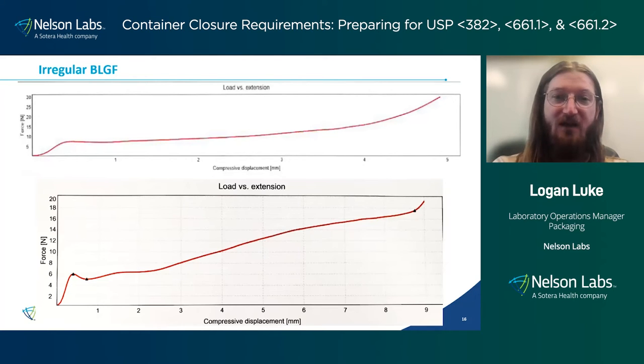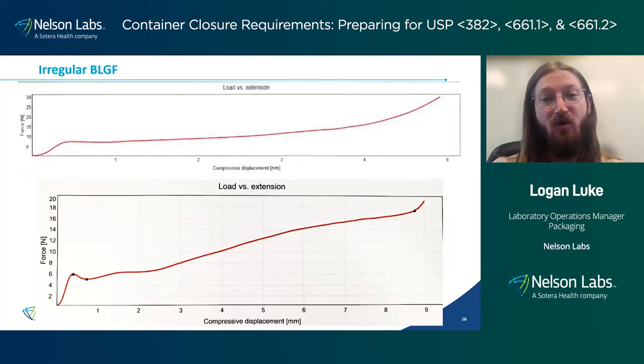What happened when we investigated this was the reason that it didn't move past the 5 millimeters is because the needle actually got clogged. We were able to verify that the needle itself was clogged, and that's why the method, when it started experiencing these higher forces, aborted the test. So these are some of the things that you can look at in order to investigate how well your break loose glide force is performing.